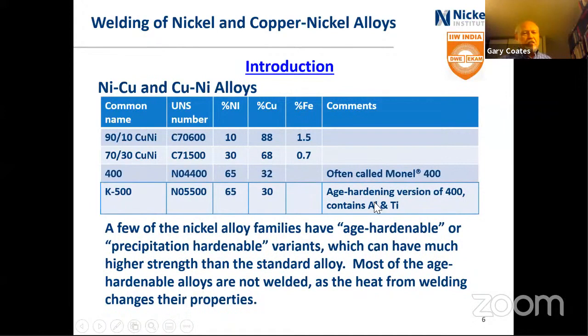Okay, now there is also another family of nickel alloys which are called age hardenable alloys or precipitation hardenable alloys. And they're like the 17-4 PH of the stainless steels. They harden, but through a precipitation mechanism. It isn't a quench and temper kind of hardening operation. You heat it up to a certain temperature, the precipitates form that make it strong and hard. Most of them are not welded because the heat from welding changes their properties. The heat affected zone, you heat it up to a temperature where the precipitates dissolve. When they do need to be welded, special precautions need to be taken. I will not be dealing with those alloys here.